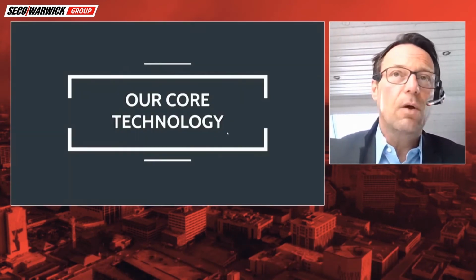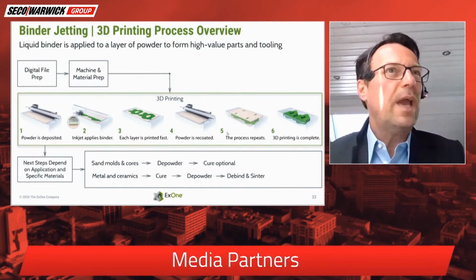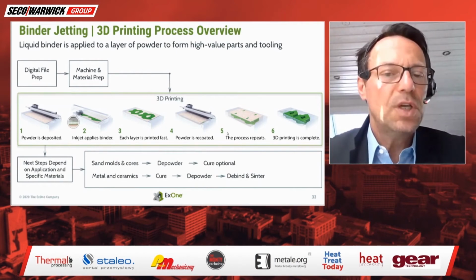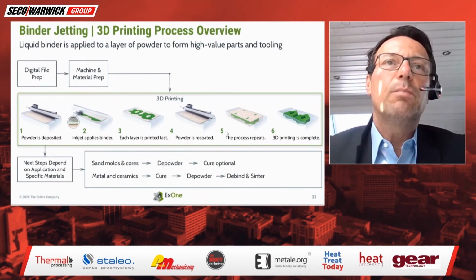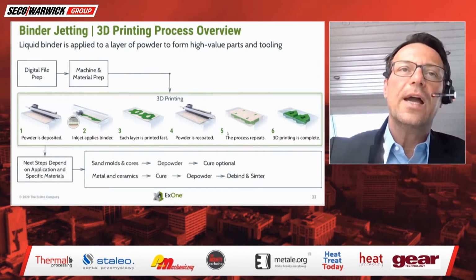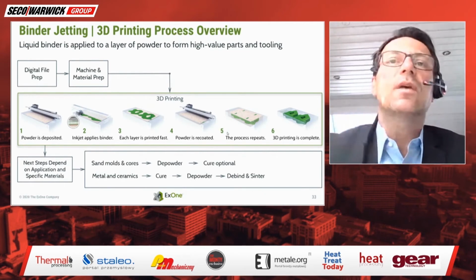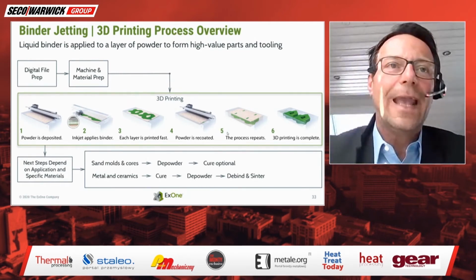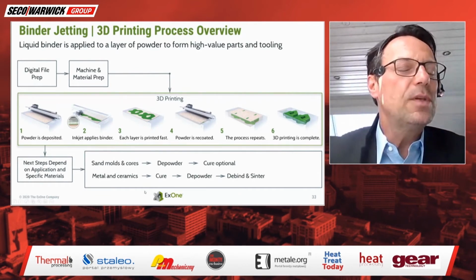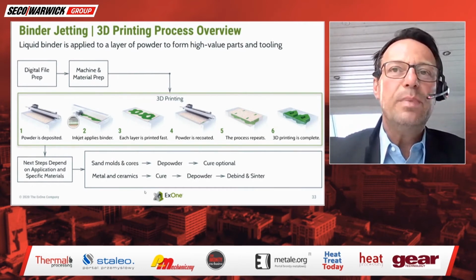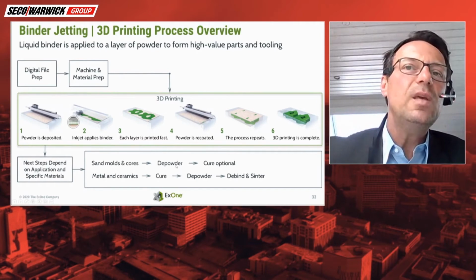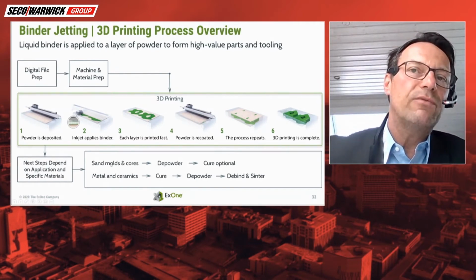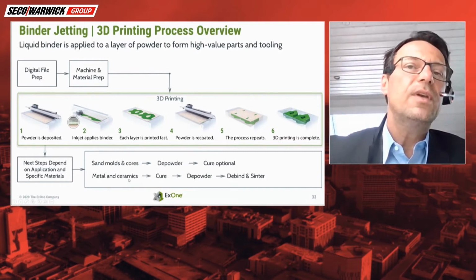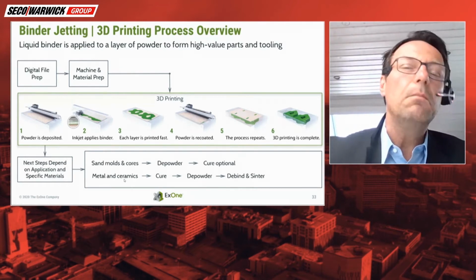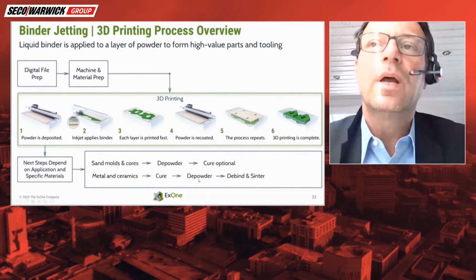Core technology. So basically we went through that already, but we said, okay, we have a digital file, we put the file into the machine and prep it, and then this is going to be the recoating step. The inkjet applies the binder. Next step, the layer is printed, and then the process starts again. And here is the difference to powder bed fusion technology based on laser or e-beam: we have to depowder our part. If it's the sand printers, we have to depowder and then cure the part. If we go for metal printing and ceramics, first we have to cure, and then we have to depowder. And after the depowdering step, we have to debind and sinter.